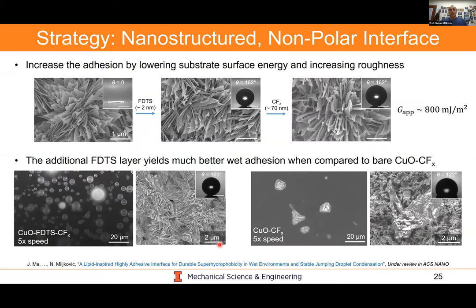What we did now is look at a structured surface. This is a copper oxide based structure. We deposit a very thin coating of a self-assembled monolayer chemistry, FDTS, which very conformally puts the chemistry down on every part of the surface. If you look at what water does on this surface, on the left it completely wets; if you promote it with FDTS, it's superhydrophobic. On top of that, we deposit another polymer layer, which forms that hydrophobic interface with very high wet adhesion. Because of the roughness, we have an apparent wet adhesion of all the way up to 800 millijoules per meter squared.